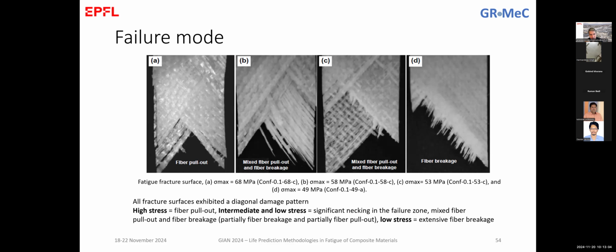The thermal increase is due to the friction between damaged surfaces. So you can imagine that in a unidirectional material, you don't have so much damage during the loading as what you have with the plus minus 45. You can also imagine that in a unidirectional material, your deformation is not so significant. So if you have reduced deformation, it means reduced friction, which means reduced temperature increases.